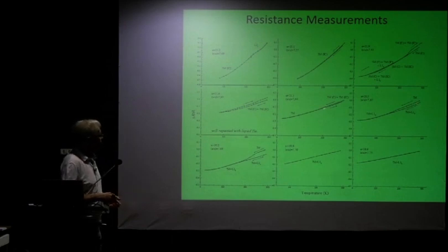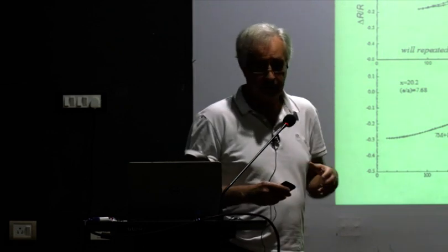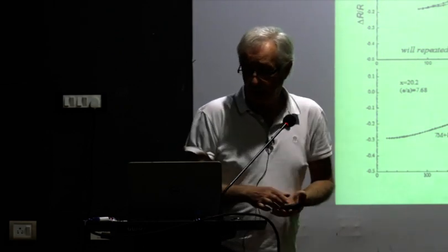And you can see that almost everywhere. In this case, for example, you have a fully closed loop. So you've come from some, I don't know whether it's properly labeled over here, maybe some 5M plus 7M state, and then you've gone down, and then the 5M has disappeared, so all around here is 7M, and when you go back up again, it remains 7M until you come to this point where the loop closes and you're back to your original state. That is one example.